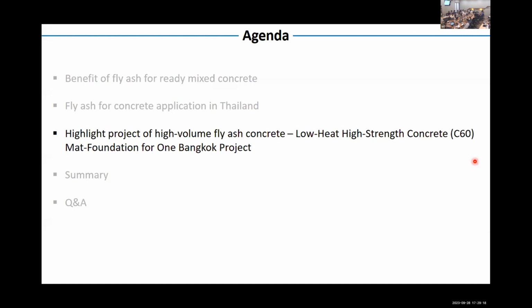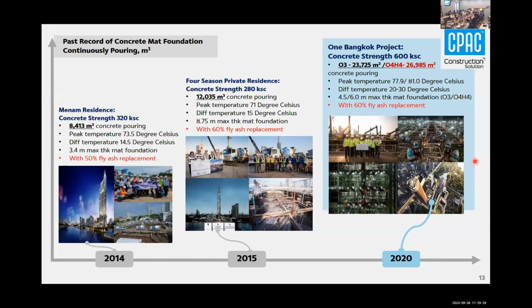So this is the highlight I would like to give you information about. As I mentioned, we use fly ash for low heat concrete structures, like a mat foundation. This is our past record in Thailand of when we produced concrete using high volume fly ash. You can see the years here, from 2014 to 2020. These are the mat foundations that we have done so far, with high volume fly ash and continuous pouring in one time.